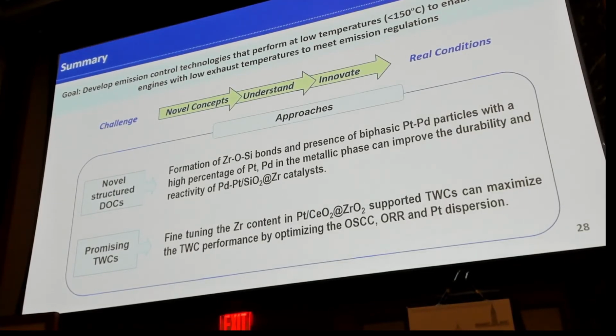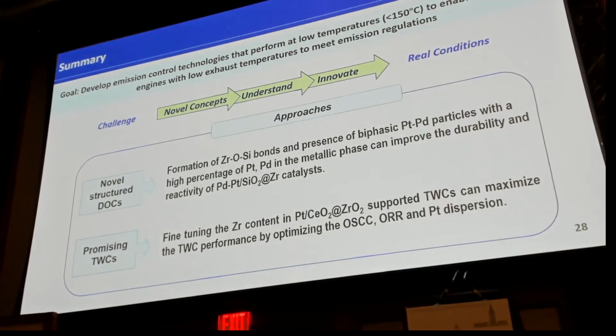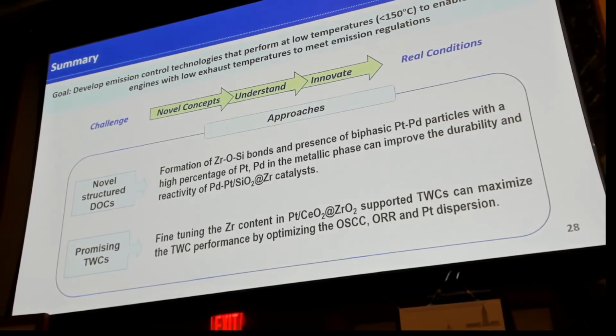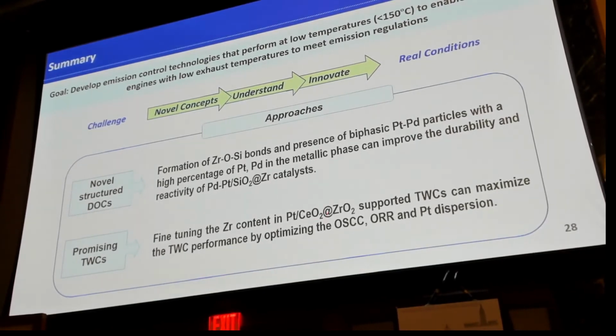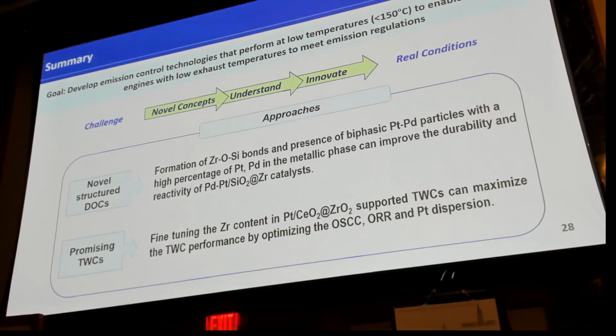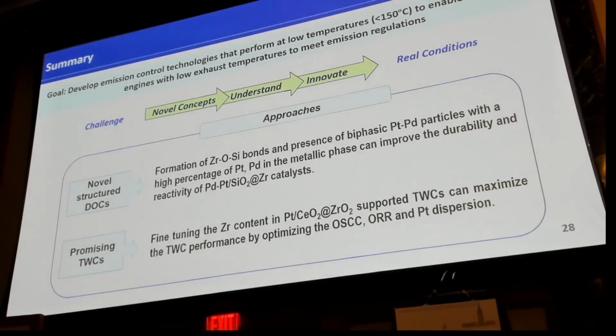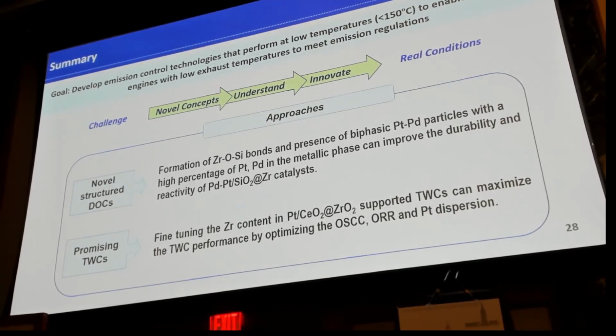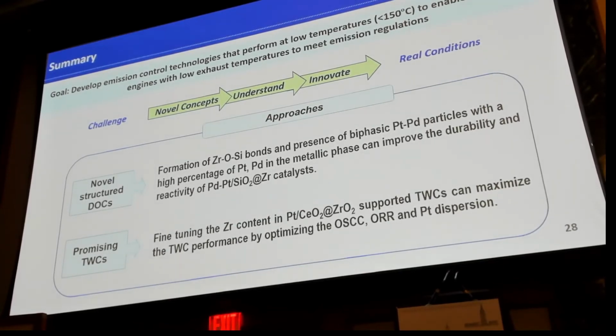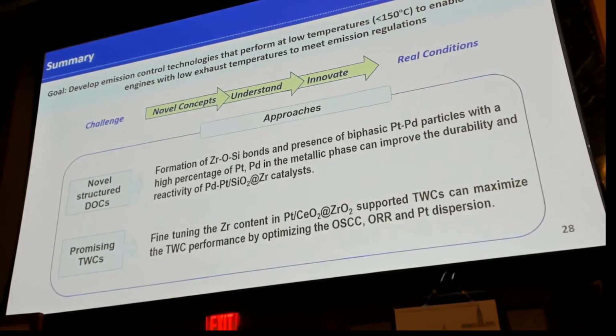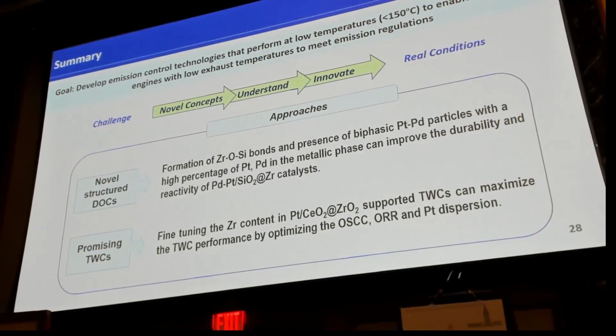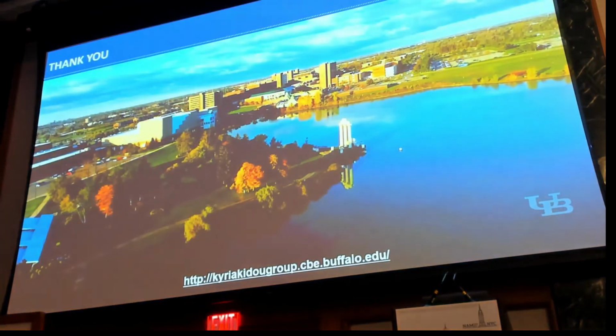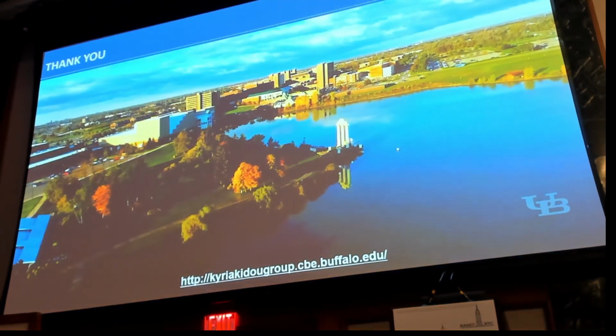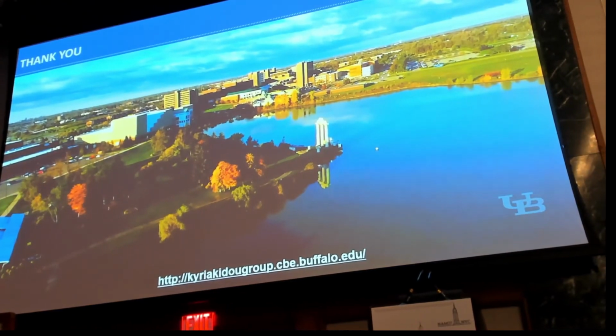And then the second part of my talk showed that by tuning the zirconium content on the platinum supported on the ceria and zirconium catalyst, we can maximize the performance of the three-way catalyst by optimizing the platinum particle size, dispersion, oxygen storage capacity, as well as the oxygen releasing rate. With that, I would like to thank you for your attention, and I will be happy to answer any of your questions.